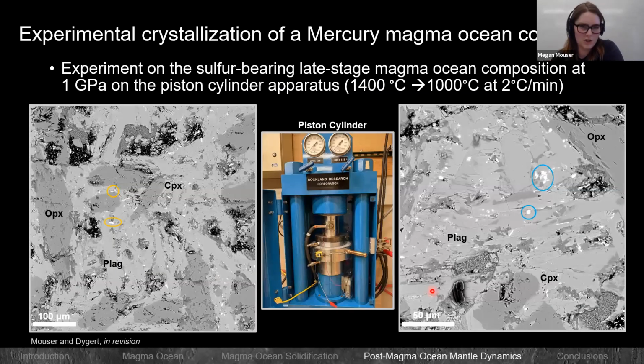So one thing that we wanted to do was just test what types of sulfides we could precipitate, because it's not really well constrained in a lot of ways. So we decided to take that sulfur bearing composition that we had from our magma ocean experiments and test a crystallization experiment at 1 GPa. So we used the piston cylinder, went from a superliquidus condition of 1400 down to 1000 degrees C at a fairly slow cooling rate so that we could promote crystallization.